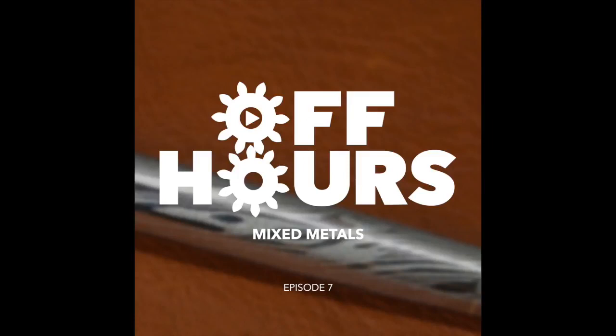It also became quite decorative because you're combining these layers of metal together. You can then etch away one of the metals a little bit, and so you then reveal this grain structure. And depending on how you weld the bars together, what shape the bars are in, what you do to the bars afterwards, that all reveals a different grain structure in the metal. And so you get some beautiful shapes and grain out of it, and it looks very much like a wood grain when you're finished with it. Yeah, it's a good way to describe it.